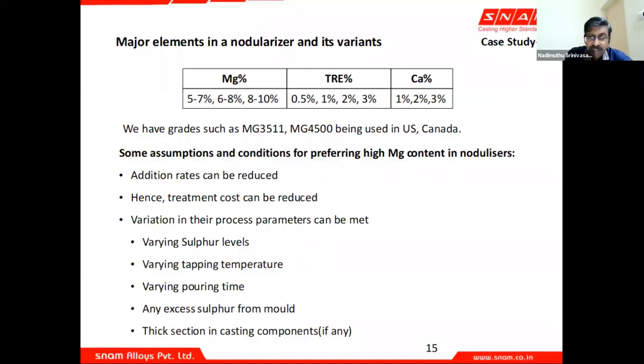And whatever we have seen from our supplies and visiting customers who are buying, in the US and Canada, the grades are 3511 and 4500. 3511 is 3 to 5% magnesium. Look at that as a comparison between 8 to 10%. And 4500, of course, is a specialized grade where for some thick section, people do not want to use rare earth. But look at the magnesium percentage, it is only 4 to 5%.